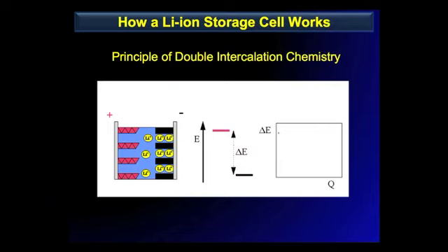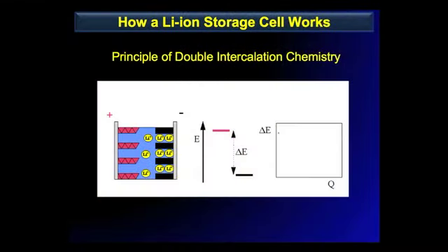Now this cartoon is carefully designed such that it marries this process. So this is the process on discharge, and the voltage goes down in the cell, and then we recharge the battery, we shove the lithium back into the carbon, and it comes back up again. And you can see that the energy difference between those two electrodes actually changes as a consequence of the fact that the Fermi energy of this positive electrode is changing. So we call this a double intercalation cell. Sometimes the Japanese used to call it a shuttlecock cell.